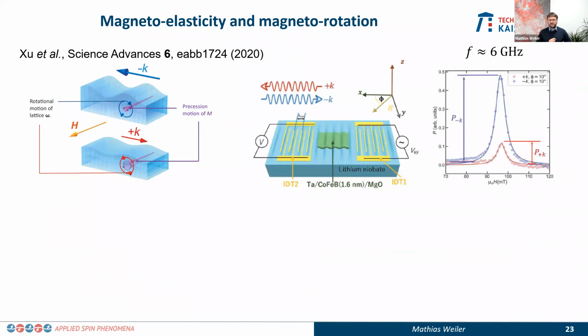And that has been experimentally realized first by Mingrang Xu and co-workers about 2 years ago, and they used a thin film of cobalt iron boron. Okay, so very similar to what we looked at, and they showed that indeed they observe a strong non-reciprocity of the transmission from left to right and right to left, so identical to what I showed you before, and they ascribe this non-reciprocity to the existence of such a magneto-rotation coupling. Okay?